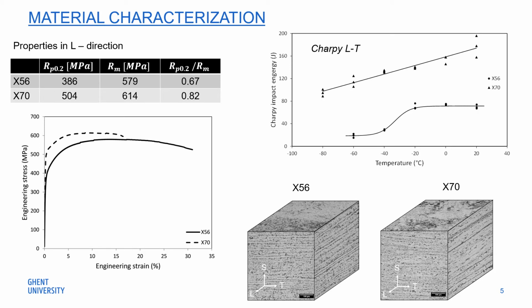First, our two materials were characterized. Tensile tests were performed in the longitudinal direction, showing that the X56 steel has a larger ductility and a larger strain hardening than the X70 steel. Charpy toughness tests indicated that the X70 was significantly tougher than the X56 pipeline steel. A microstructural characterization shows a heterogeneous microstructure typical for rolled steels.